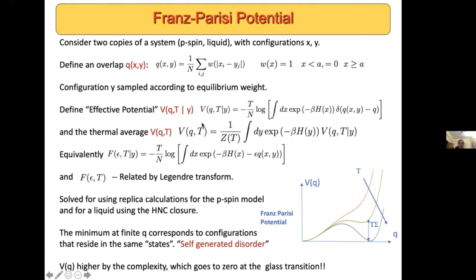And this effective potential can then be averaged over the equilibrium distribution of the second copy. And this can also be done in different ways by applying a pinning field that is proportional to the overlap instead of fixing the overlap to have a certain value when you do this evaluation. But basically what one gets is this Franz-Parisi potential as a function of Q.